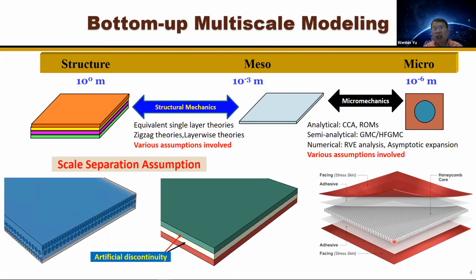do a micromechanics calculation to get the material properties for that honeycomb. Then we treat it as a homogeneous layer to do a sandwich structure analysis. And it will have some issues even for the global behavior.